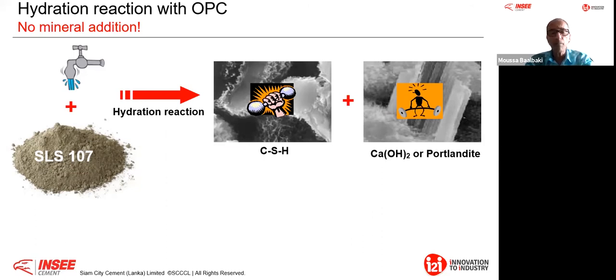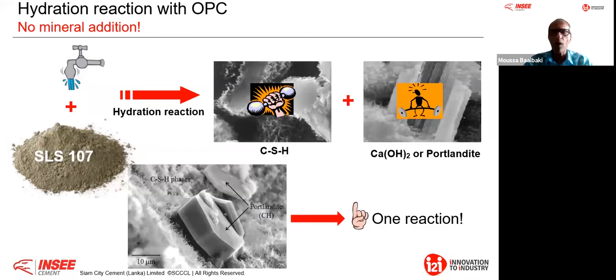That is why, if you look at mix designs in the past, they were sometimes rich in cement just because they needed to ensure they had developed enough CSH. That is the main reason. Therefore, when I look at this SLS 107, you have one reaction, and this reaction will produce a very good product called calcium silicate hydrate, as you can see in the microscopic picture here from the scanning electron microscope, and portlandite. You see already in terms of size how the portlandite is a very big, very soluble salt crystal compared to the CSH, which is at the nano size.